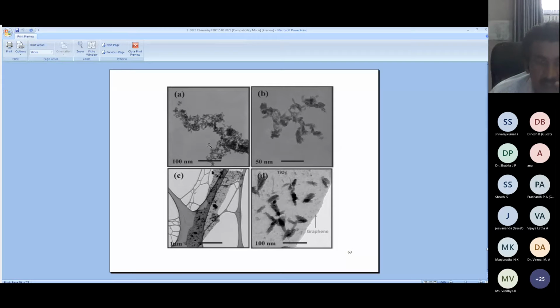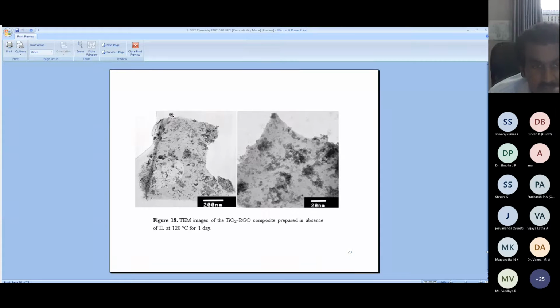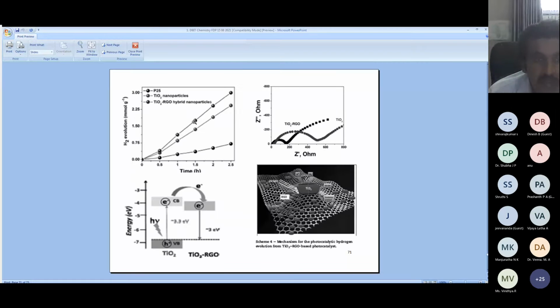Right, now just see here, this is the pure TiO2. We are going to get a bead-like material, and then this is TiO2 RGO in the presence of graphene sheet. Right, this is the graphene sheet, and these are the TiO2 particles. You can clearly say that TiO2 nanoparticles are embedded on the surface of graphene. Right, just see here, it is very nice, right? Okay, these are the TEM images for the presence of TiO2 nanoparticles on the surface of graphene. Even when you are looking at that, this is P25 commercial TiO2, then this is TiO2 nanoparticle, and then this is TiO2 RGO hybrid, and commercial TiO2 also shows hydrogen generation, right?